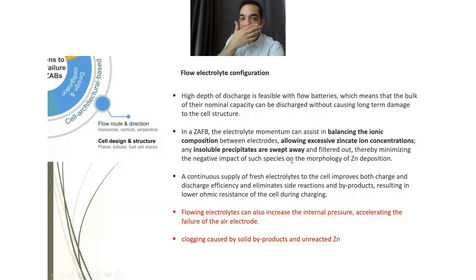The first thing is the introducing of flowing electrolyte. The first advantage it gave us is that the high depth of discharge is feasible with flow battery, which means that the bulk of their nominal capacity can be discharged without causing long-term damage to the cell. And also, we know that the electrolyte momentum can balance the ionic composition and also regulate the current density in a diffusion layer. So in that case, the morphology will be smooth when using the momentum of circulating electrolyte.